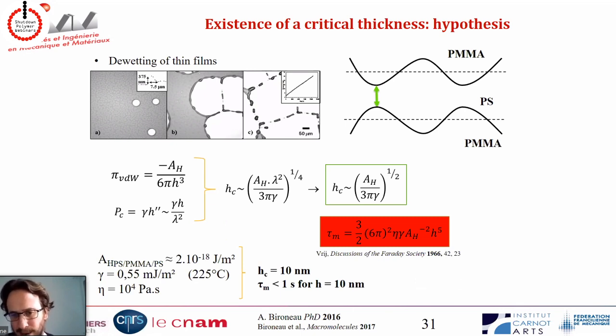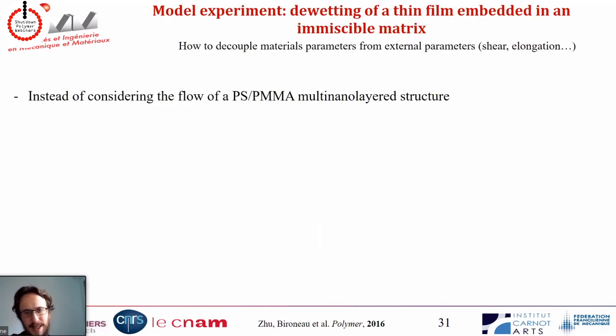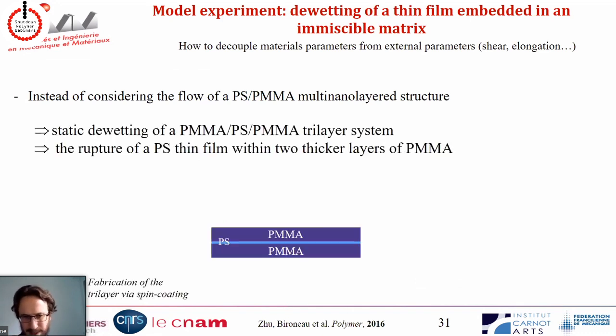And also the time at which it breaks, the equation is written here, and I will not detail it, but if you put some numbers in there, you can see that the typical time is about 1 second. And that's really short, because the extrusion process lasts 1 minute. So if everything breaks in 1 second, then at the end of your extrusion process, everything is broken. I'm not going to present that because it's already 45 minutes, so I'm going to skip that part, but you can check it later on.